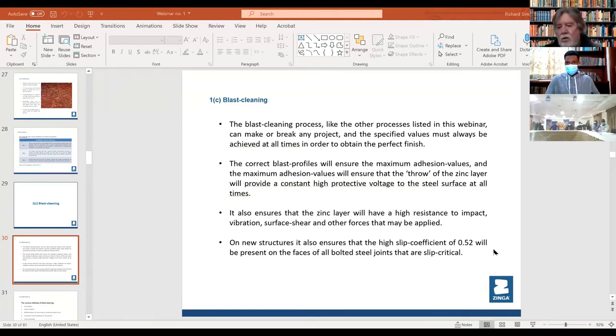Epoxy zinc paints will crack, they will split and flake. But because Zinga is very compressible, and especially on a good profile, you can hit it with a hammer, literally with a hammer. I used to do demonstrations and hit it as hard as I could. And people were amazed. The zinc would never, ever crack. And it's all down to the good profiling when you're blasting. And again, if you have the right blast pressure, you're using the correct grit, like Black Beauty that we used on Akosombo, you'll always get a perfect profile every time. So it's not a problem.